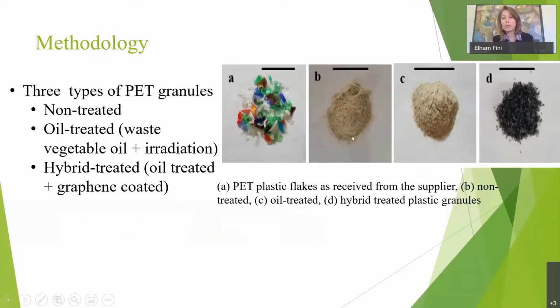We treat it with oil here in the second picture. We grind it to the exact right size, and in the final part, we actually hybrid treated it with carbon, which made it super compatible. Both C and D pictures here, both products are compatible with the construction material. The one that has carbon coating has certain additional benefits, which I'll talk about in a minute. The one that has carbon, we call it hybrid because it has oil followed by carbon coating. The one that is just oil, we call it OTPG, which is just oil treated. Both oil treated and carbon treatment help with compatibility.